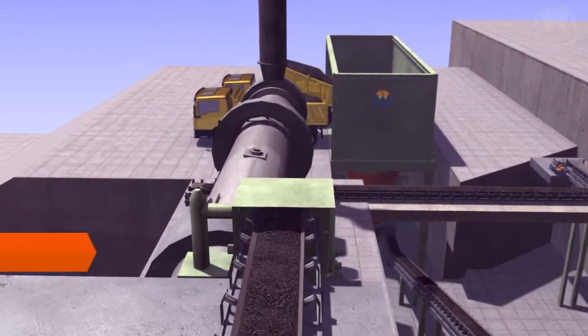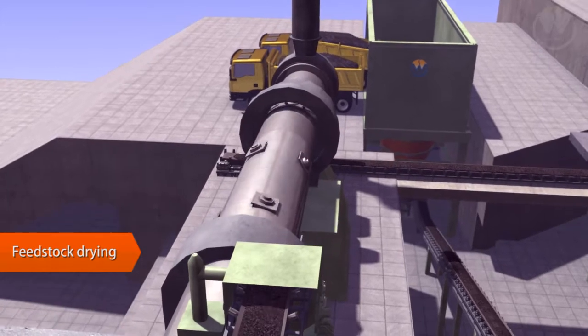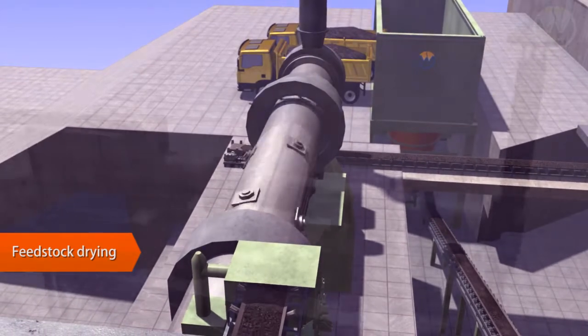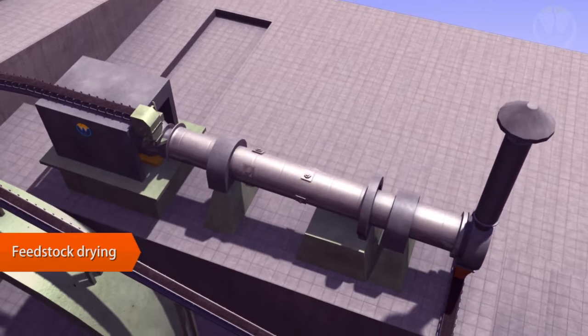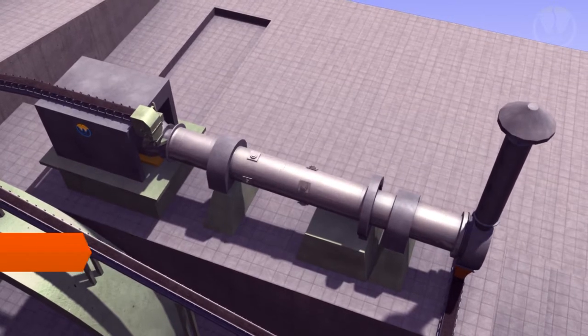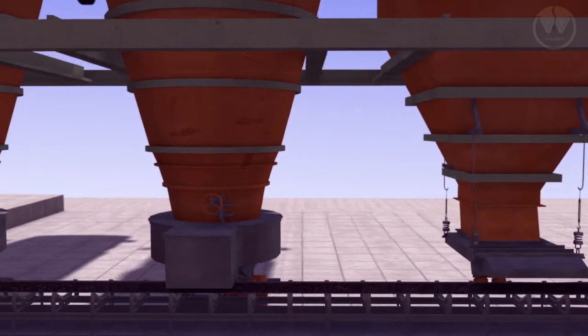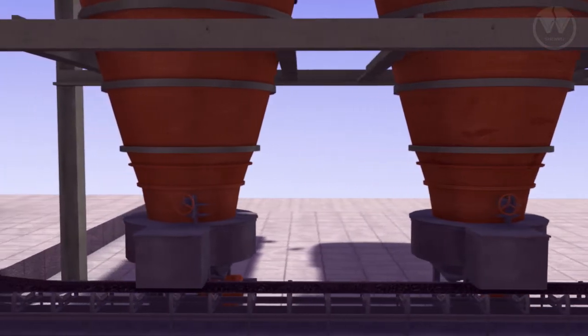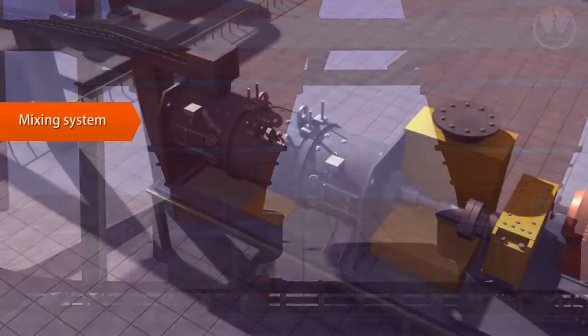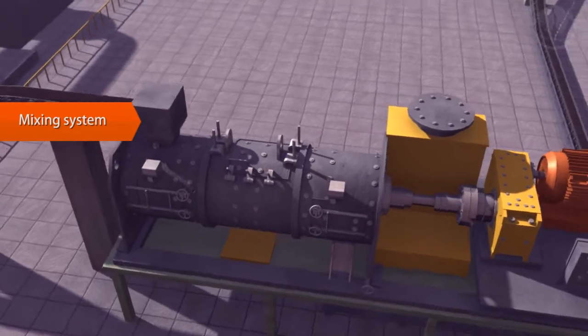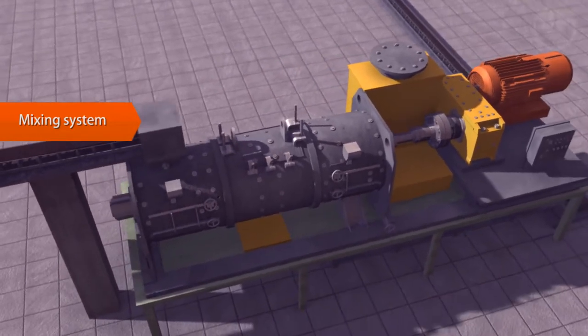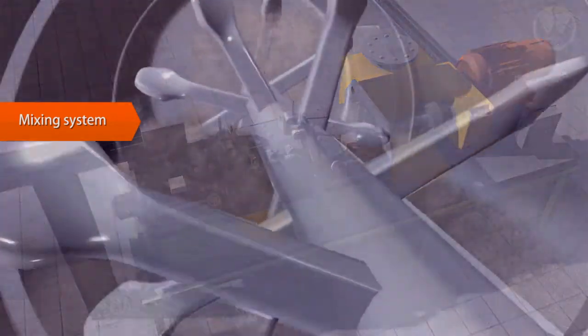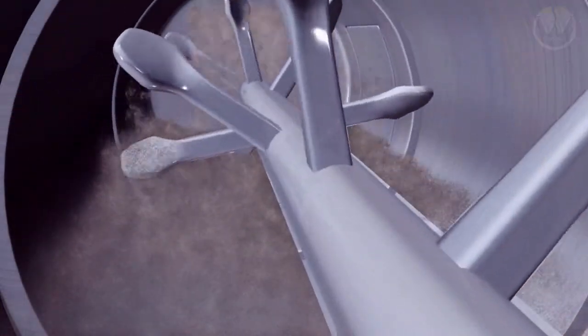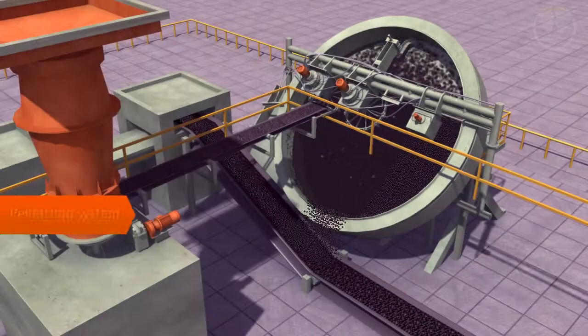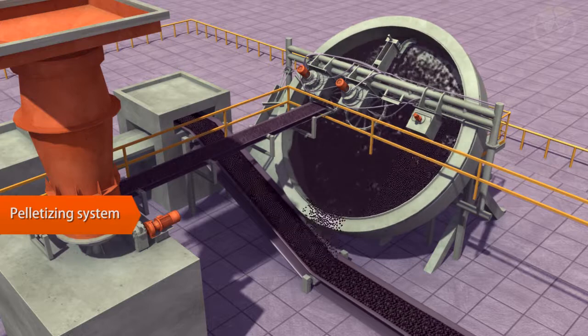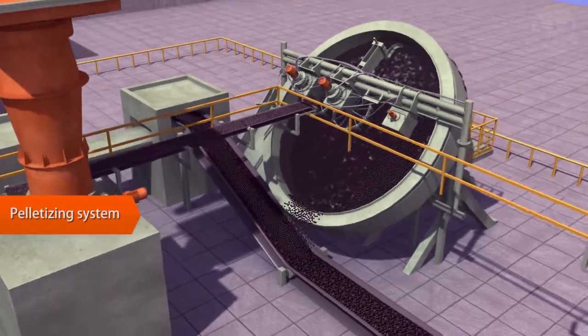The feedstocks are sent into the dryer via the feeder. The dried materials are sent into the proportioning bin via feeding belt conveyor. The binder is uniformly sent into the intensive mixing system via the feeding belt conveyor. After mixing in the mixer, the materials enter into the pelletizing system to make qualified carbonaceous pellets, which are then sent into the green pellets drying system.